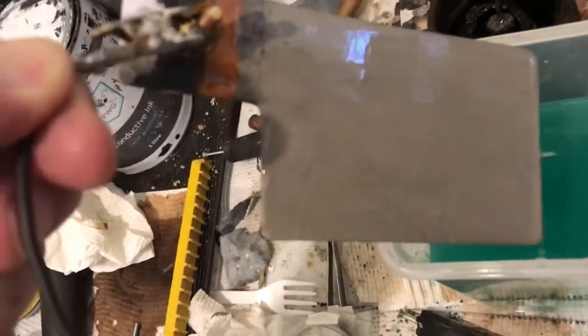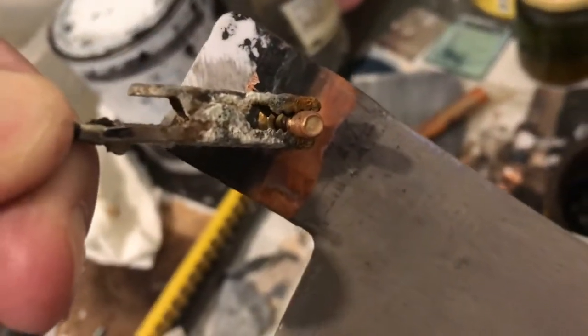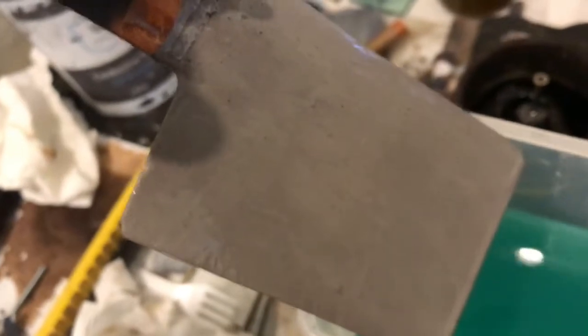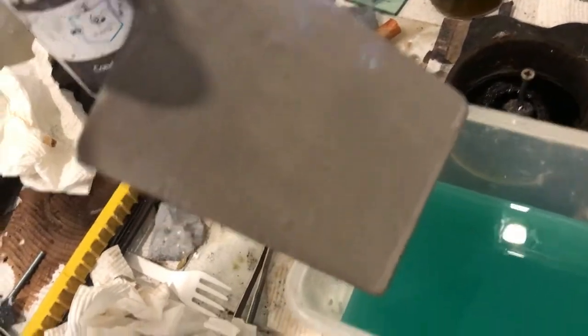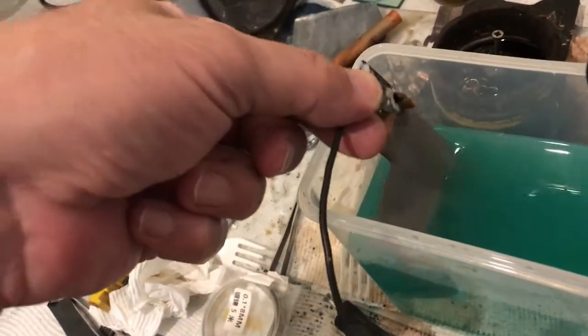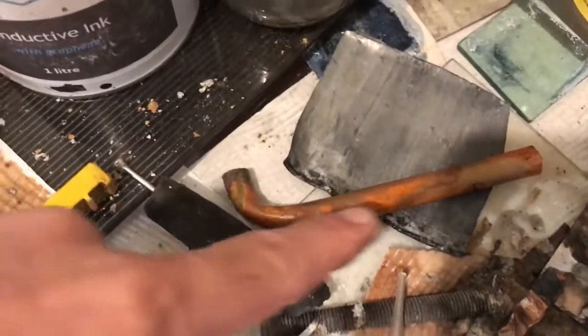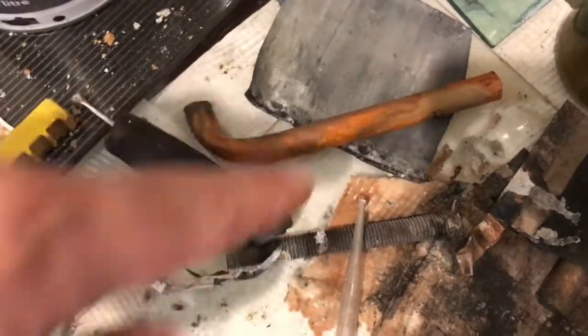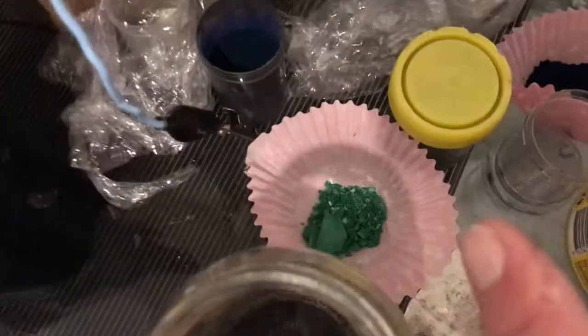And we got a layer of nickel already. You can see the copper plating down there. I took the copper plating right up. That measured from that top bolt all the way to the bottom 0.1 ohm. So that was pretty impressive. And I used this as my anode. And it didn't really use a lot of copper. So I'll plate both sides of that, and then I'll use some nickel hydroxide.